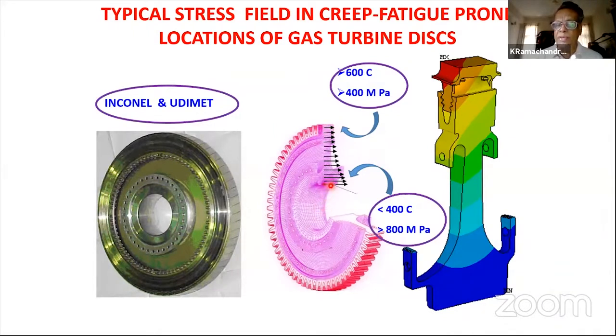Whereas the bore, which is the center part of the disk, the hub of the disk, has very high stresses, 800 MPa, maybe 900, depending on the type of loads that we have, depending on the material. But the redeeming factor is that the temperature is quite low, 400 degrees centigrade. So the temperature is low, but stresses are high. And therefore this area becomes fatigue critical.